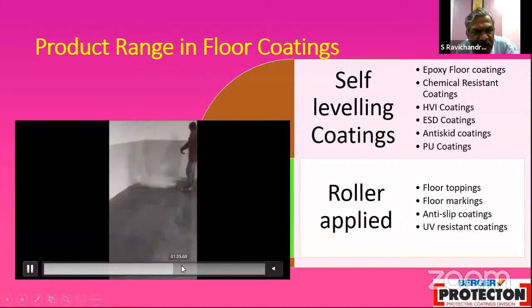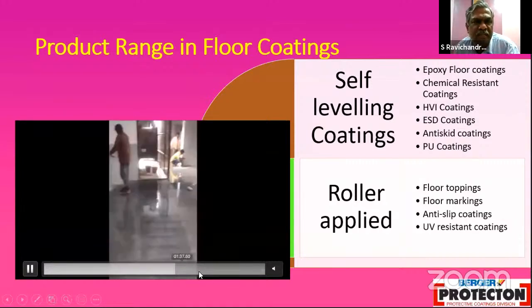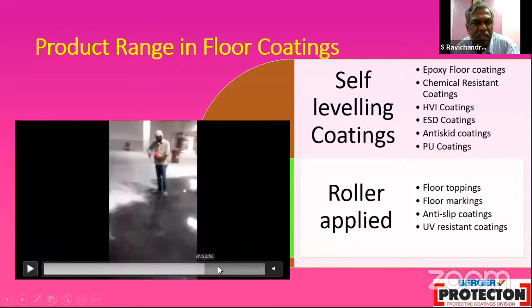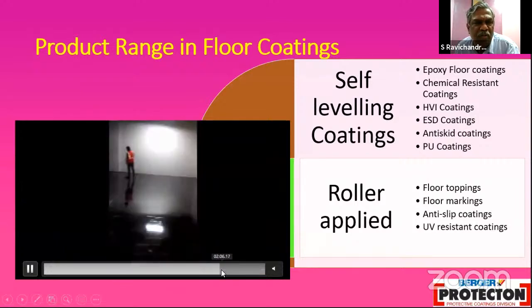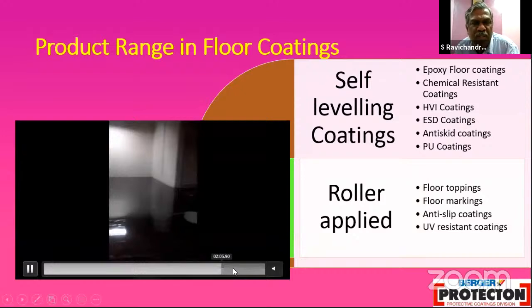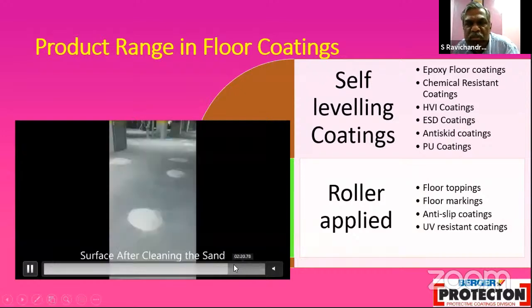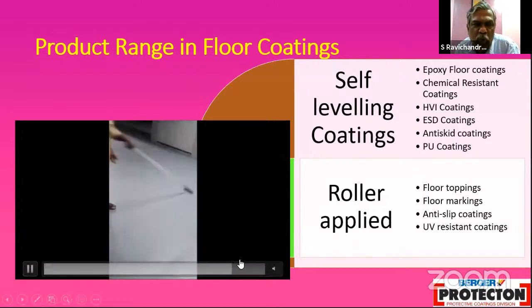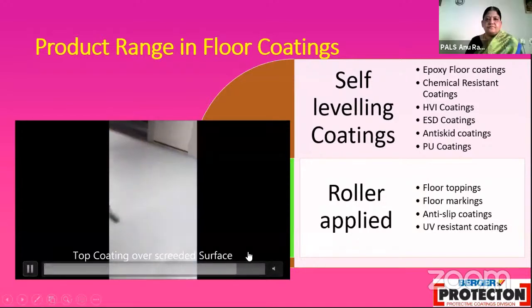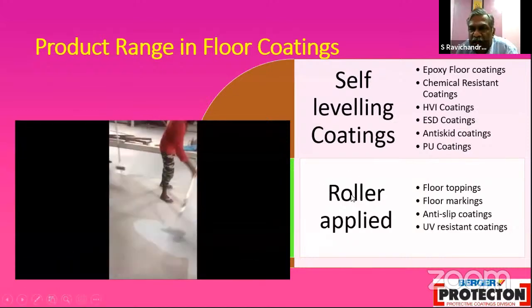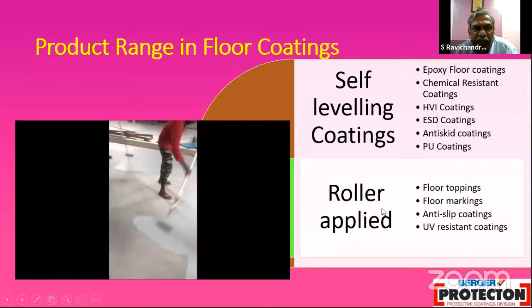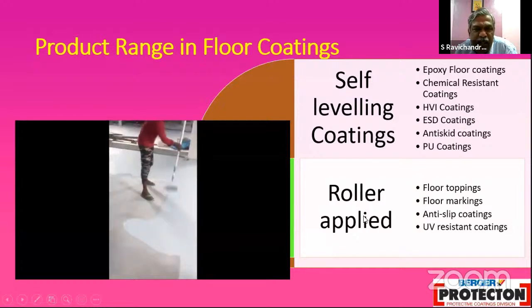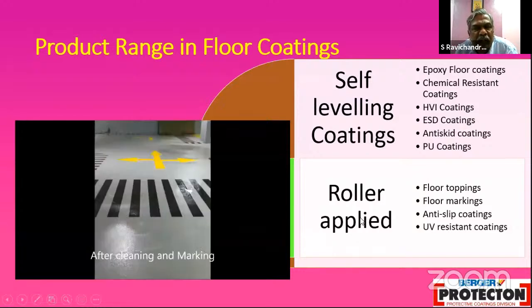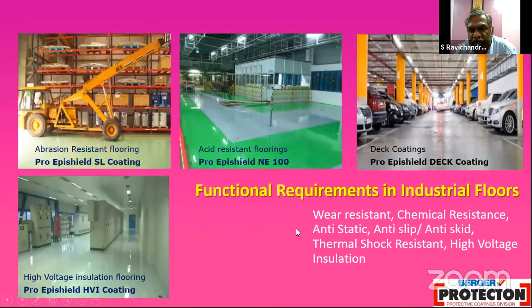And now this is a process called broadcasting, where they are putting an amount of aggregates to give you the roughness, and subsequently they'll be doing a floor coating which is applied at a 2 millimeter thickness. So this can take heavy duty floors, more than 20 metric tons of load it can take, and these are going to protect your concrete for not less than 10 to 15 years. These are all specialized coatings for the floors. There are a lot of applications for floors. Your tiles is not required. This is a seamless continuous material.